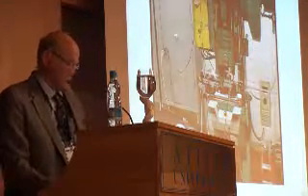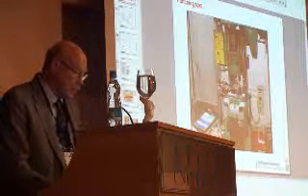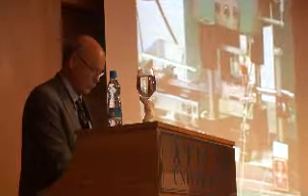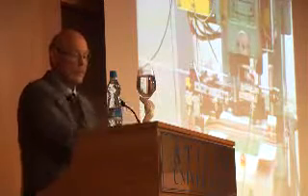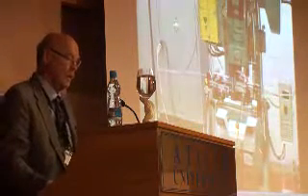Coming to process tests, I'll only mention our punching test. So you see the punch being drawn automatically with a speed of 150 strokes per minute. And we measure the punch load as well as the backstroke force during the test, as you'll see in a minute. This is one of the punches. There are two punches at the same time. You see the punch load and the much smaller backstroke force, and we take out the maximum backstroke force and plot here for each of the two punches, making two holes, to see how it develops.